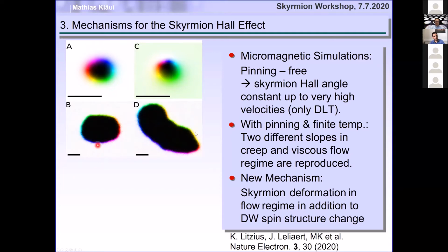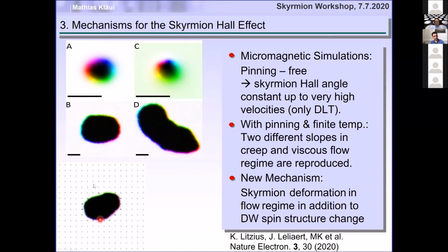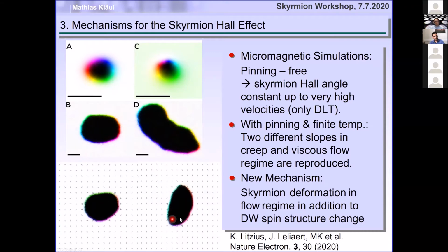at rest relatively round, but when it moves, it gets elongated. And so we have this mechanism where, if you look at the skyrmion at low speed, it moves through some pinning sites and deforms a little bit and grows, but otherwise stays round. And at high velocities, you can see that it elongates. So you'll see this simulation will start in a minute as a round skyrmion. And then after a few nanoseconds of motion, it has actually turned into this ellipsoid.